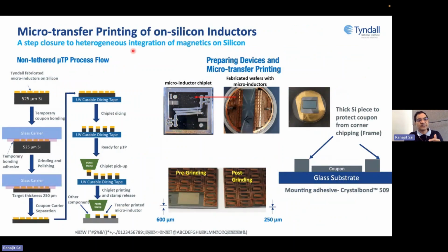We had to come up with a non-tethered, new process where we are backgrinding the substrate after microfabrication of the inductor with a glass carrier, and then backgrind it down to 250 micron. We can backgrind it to 50 micron, but here we have used 250 because the other capacitors were 250 micron thick. So to match the thickness, we then use a PDMS stamp to pick it and place it on some foreign substrate, something like one wafer you have, and you pick from another wafer and place it over here.